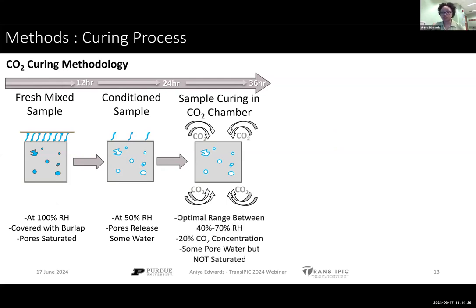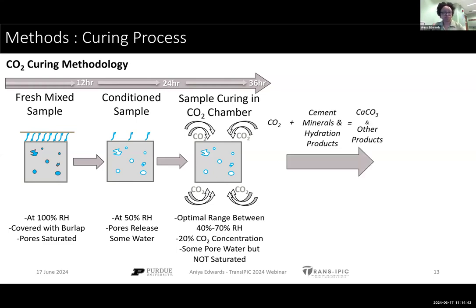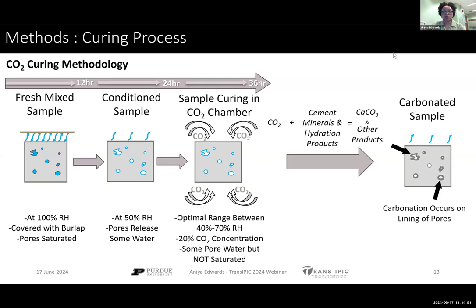The optimal range is between 40 to 70% relative humidity. And that allows for some of our pores to have some pore water within them, but it's not completely saturated because we need some space for the CO2 reaction to happen. And what happens is that CO2 reacts with some of the cement minerals and hydration products to create calcium carbonate, along with some other things. And this in turn results in a lining of our pores with calcium carbonate and a release of water as well.